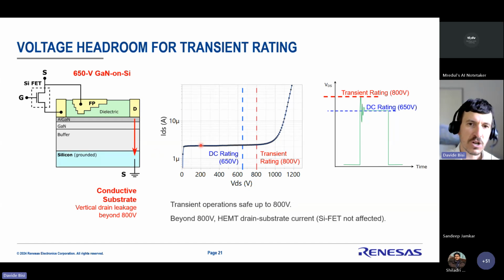And you can see here the off-state curve of the device, and you can see that the leakage begins to increase at around 900, 1000 volt. And the reason why there's leakage beyond 900 volt is not because of avalanche, because we don't have any p-GaN, there's no avalanche in lateral GaN, but because of the leakage between the drain and the substrate, which is connected to the source. So beyond 900 volt, we have leakage between drain and substrate. And so that's why we are rating the device very safely. So the DC rating is 650 volt, and then we have a transient rating at 800 volts that is there to allow any spikes or overshoots, to make the device reliable and robust to these over-voltage events.